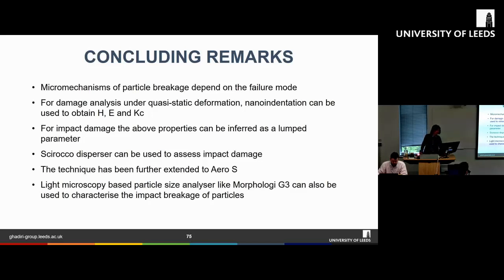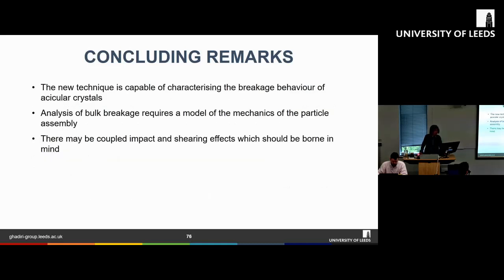We can also use a light microscopy-based particle size analyzer like the G3 to characterize the impact of crystals. The new technique is capable of characterizing the breakage behavior of acicular crystals. Analysis of bulk breakage requires a model of the mechanics of the particle assembly, and there may be coupled impact and shearing effects which should be borne in mind. So if you have a process in which particles undergo different types of stressing, be careful, because what you get might be very different from what you expected.